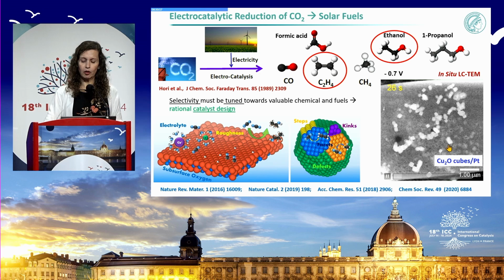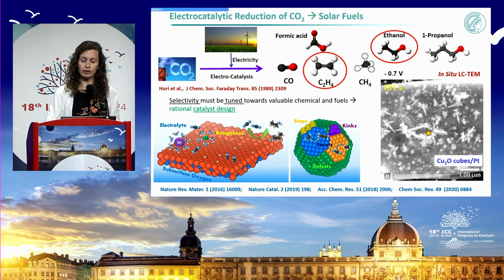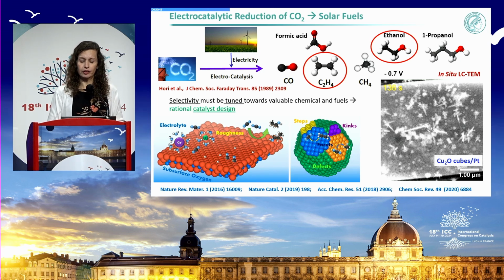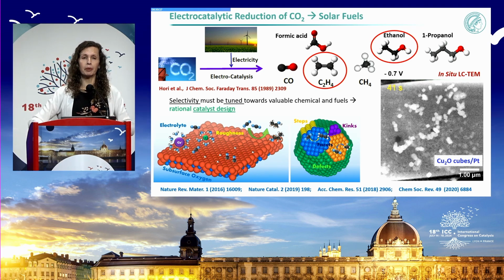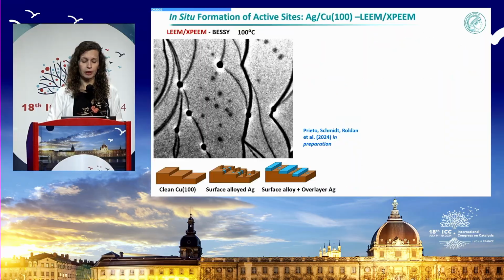And you're going to see how my very nice initial catalysts are actually changing under reaction conditions. You see the formation of these dendrites. You see the splitting of these cubes. So whatever I synthesize is evolving under the reaction. And in this case, this is very strongly dependent on the reaction time. It's strongly dependent on the electrolyte. It depends on the support that you have underneath. So all of this needs to be considered.